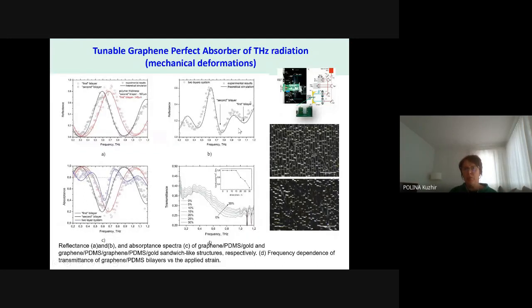When you change the conductivity of graphene, the position of the perfect absorption peak tunes. Another way to tune the perfect absorption is to put graphene on top of a flexible, stretchable substrate like polydimethylsiloxane (PDMS). Through mechanical deformation you change the thickness of the layer beneath the graphene, easily tuning the position of the absorption peak. For instance, changing the PDMS thickness from 100 to 120 microns shifts the absorption peak from 1 terahertz to almost 0.6 terahertz.